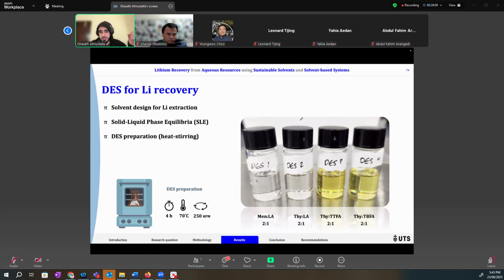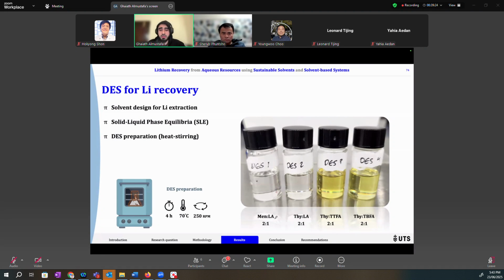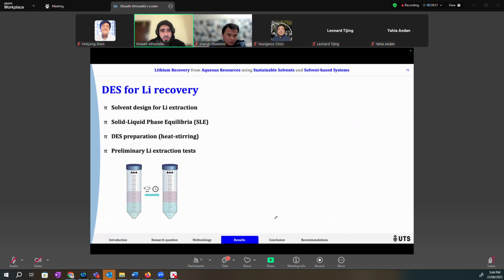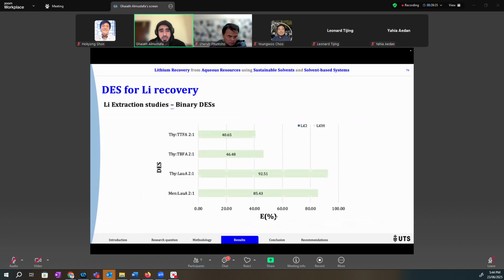So the preparation of the DES is, as I mentioned, one of the properties of DES: the simplicity of synthesis. You just mix the components together at a particular temperature, usually 70 or 80, and you shake them for a period of time, and then the result is a different set of DESs that can be used for your extraction. So we started by testing such particular solvents to see their efficiency in lithium extraction.